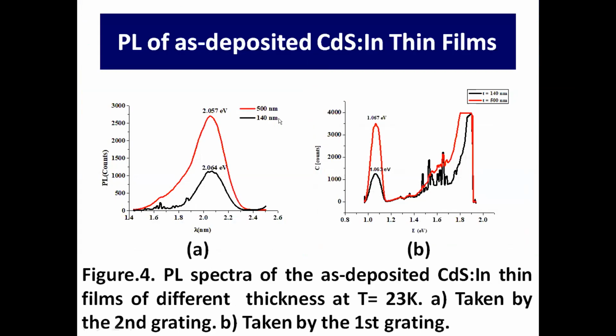Now this figure shows the PL signal or PL spectra of the same two films, which are here as deposited. You see the red line for the thicker film and the black line for the thinner film. Now here in part A, the broad band represents the yellow-red bands, and in the other one, this band is the infrared band. Now the yellow band is centered at about 2.057 electron volt for the thicker film and 2.064 for the thinner one. The infrared band is centered about 1.067 electron volt for the thicker and 1.063 for the thinner one. As you see, the photoluminescence spectrum has higher intensity for the thicker film but lower for the thinner.